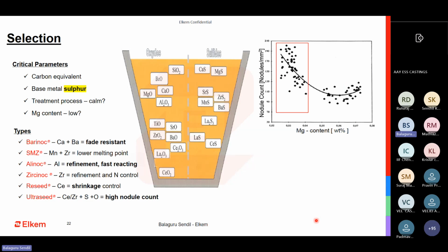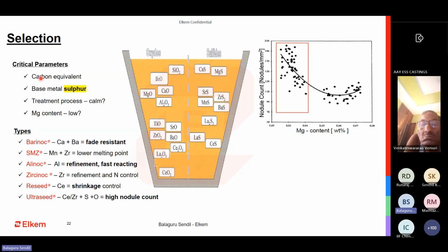Selection of inoculant is very important. Why do I select this inoculant? Carbon equivalent is a very important factor for selecting an inoculant. If you're having high carbon equivalent and you're adding too much inoculant, 0.5, 0.6, the silicon from it is going to affect your carbon equivalent, and you might end up getting oversized nodules, which could result in shrinkage. So carbon equivalent is very important.